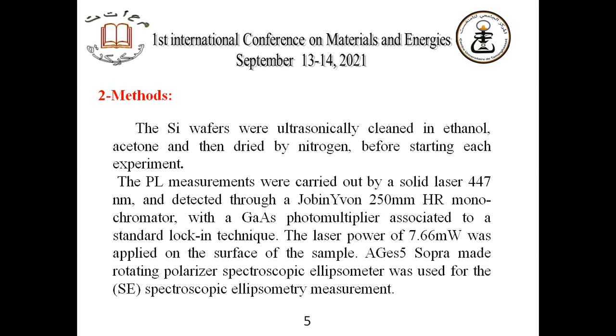The used electrolyte is a mixture solution of hydrofluoric acid and ethanol. The silicon wafers were ultrasonically cleaned in ethanol, acetone, and then dried by nitrogen before use for starting each experiment. The PL measurements were carried out by a solid laser and detected by a monochromator with a photomultiplier associated to the standard lock-in technique.